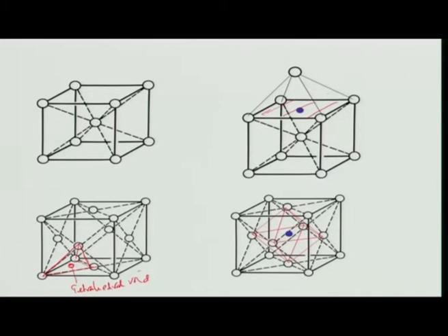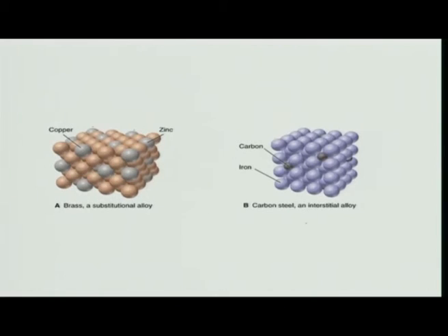Okay. Similarly in FCC unit cell at the center there is an octahedral void. See, I have drawn the octahedral voids. So carbon atoms actually go into these voids. They sit there, and that is why this is known as interstitial solution. Steel is known as an interstitial solution.